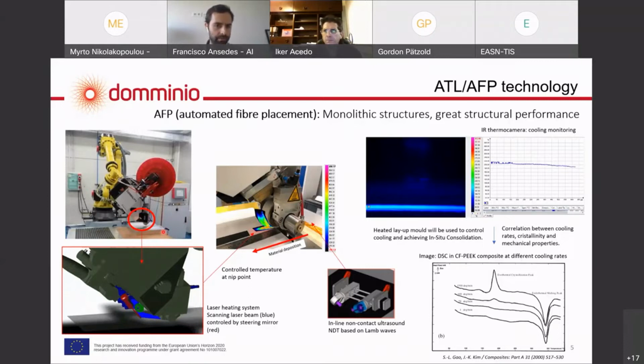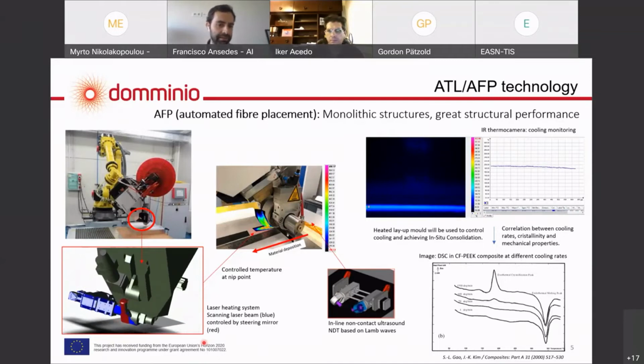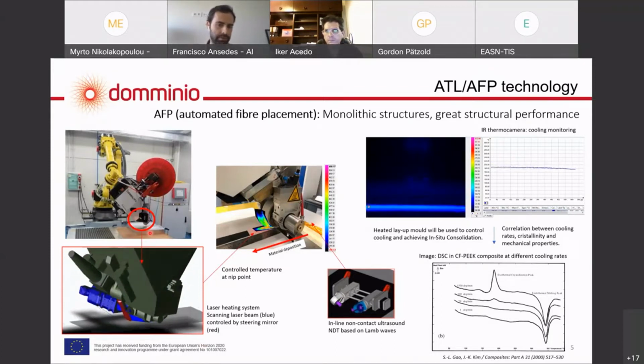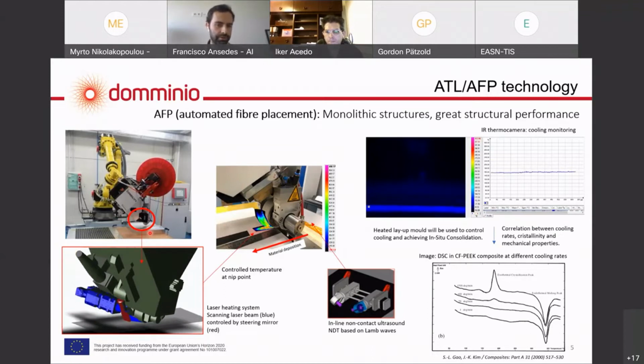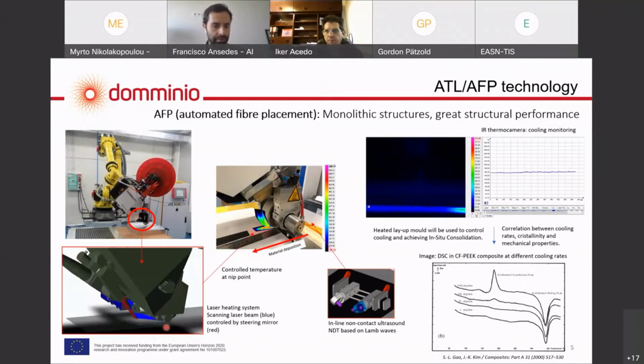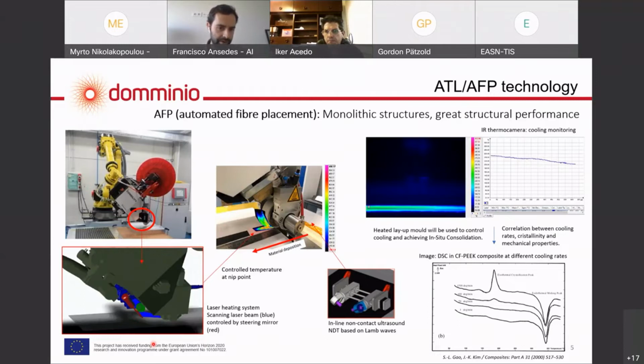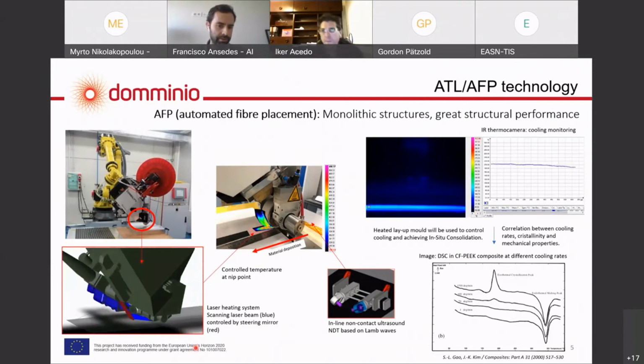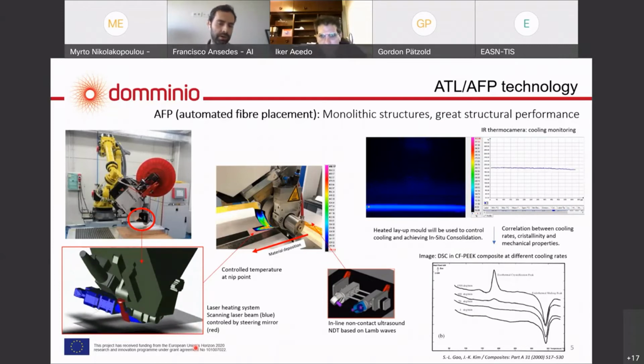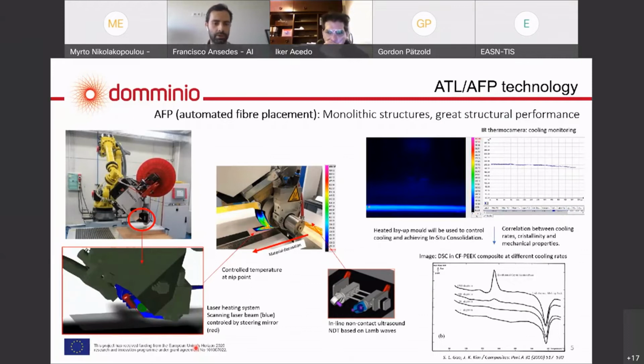To start, we are developing an innovative laser heating system in order to obtain the desired temperature in the composite. We are working between 300 and 400 degrees, and we have to heat up the composite tapes. So we are developing a laser scanning system, the red part you can see here, that controls a laser beam, in blue, that will scan across the width of the tape. At each point we have a controlled temperature, regulating the power applied to each point, so we have a uniform temperature across the width of the tape.